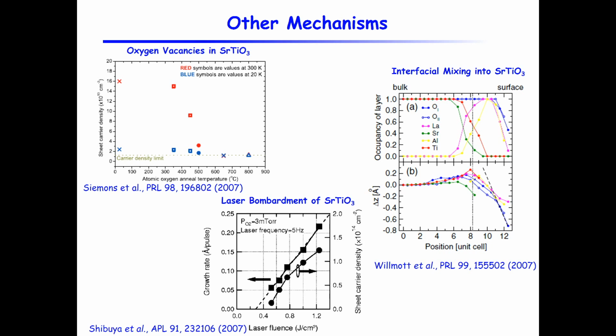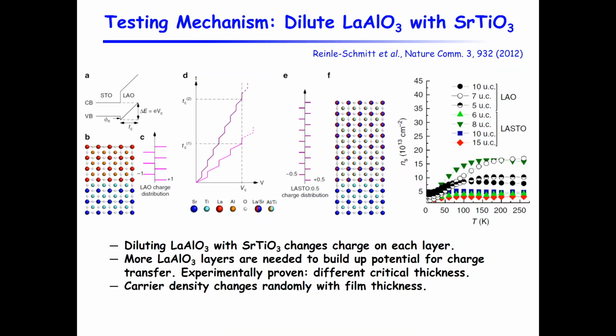When you bombard it, it becomes conducting without even the top layer. And then there are proposals of interfacial mixing between the lanthanum aluminate and the strontium titanate. People know that when you dope it, it becomes conducting. And so in this area, the mechanism of these 2D electron layers, there's no consensus about what is really causing that.